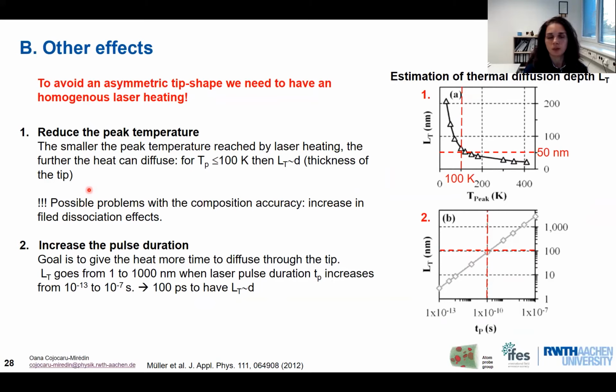It's simply by fulfilling two strategies. First of all, we need to reduce the peak temperature on the tip. There was a nice work done by Müller and Cojocaru, where they showed that by increasing the diffusion length, we decrease the peak temperature on the tip. If we increase the diffusion length to 50 nanometers, for example, which represents the radius of the tip, then we have a decrease of the peak temperature to 100 Kelvin. So this seems like a reliable work and a reliable strategy that needs to be fulfilled.